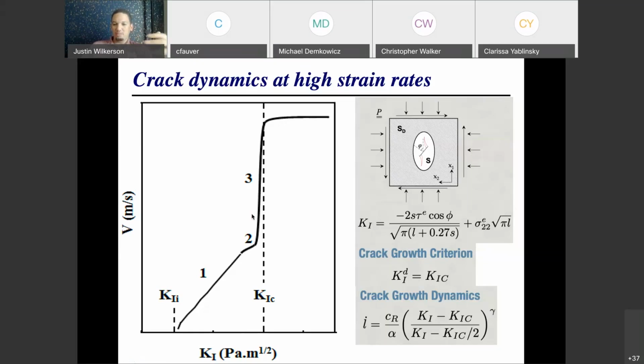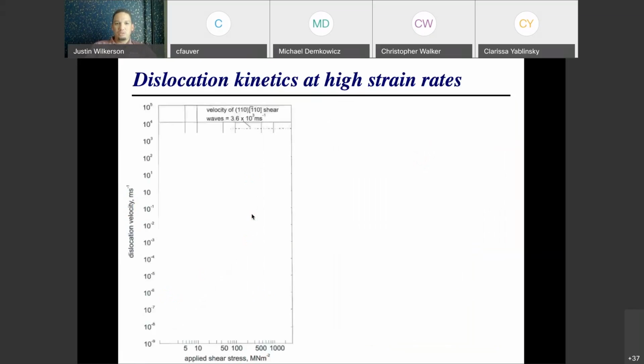From a continuum mechanics standpoint, as you're deriving these elastodynamic relationships, cracks and dislocations look fairly similar. They're both planar defects in a material. And so from that standpoint, you get solutions that look pretty similar as far as the stress fields around either a dislocation or a crack. And their dynamics are fairly similar. So next I'll show the kinetics of a dislocation, and it's generally going to be pretty similar. The main thing that's different is when we're talking about cracks, we always talk about stress intensity factors, which is a measure of the stress at the crack tip. And for every other kind of defect that we're going to analyze, we tend to think about the far field stress or the macroscopic stress on the material, or resolved shear stress on the slip plane itself.